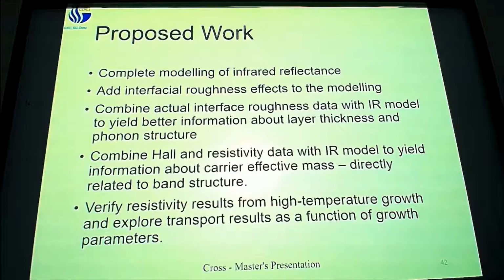I can combine this Hall and resistivity data, which can lead to carrier concentrations, with the plasma frequency that I can obtain in the IR reflectance, and I can use that to feed back to my phonon structure as well, and to my band structure, because I can find the effective mass of my carriers. I also can verify the resistivity results from high temperature growth and explore these results as a function of the growth parameters. So that's what I plan on doing going forward.